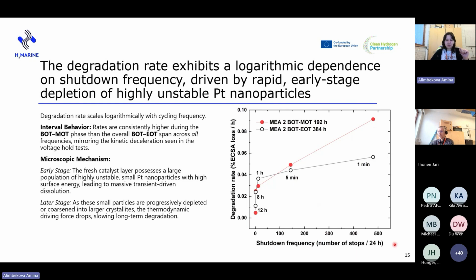For the slower cases, the degradation towards end of test is higher than in the first half of the test, suggesting that for the slower, lower frequency cases, the degradation is again in its early stage, where the fresh catalyst layer has very small platinum particles which are unstable with high surface energy, giving a big electrochemical surface area loss in the beginning, compared to the more frequent cases where they're already towards the mid to later stage, already coarsened into larger crystallites.